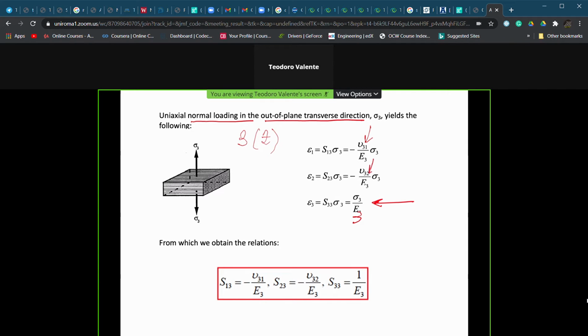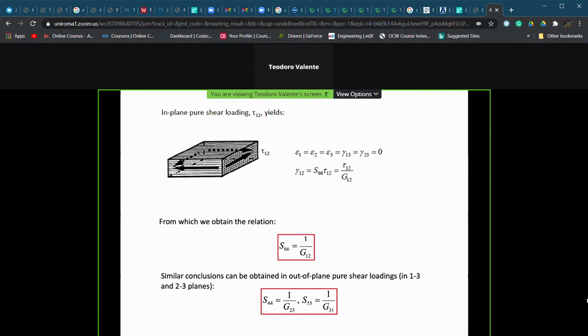Then we can estimate the value of the strains in the directions 1 and 2, the shear strain being equal to 0, by using the relative values of the Poisson ratio. This allows us to calculate the coefficients S13, S23, and S33. And so we can populate our matrix, but in order to complete the population, we need to take into account also the application of pure shear loading.